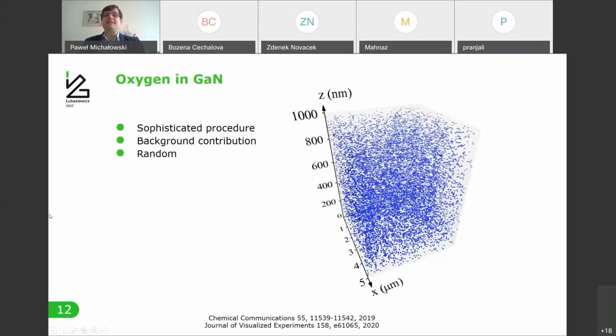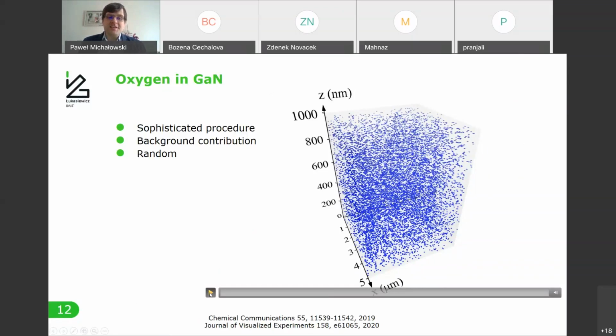sample. But the problem is that oxygen is also present in the analysis chamber of the SIMS, and we get a background contribution. I estimated that about 95% of the voxels that you see here are not actually coming from the sample itself, but from the analysis chamber. So they do not represent the actual oxygen distribution in the sample. But since the detection of this background contribution is completely random, I assumed that we may use this randomness to our advantage and basically reverse it. So after obtaining this result, I proposed to randomly eliminate 95% of the voxels of these oxygen counts from this result. And this is what happened during this reduction analysis.